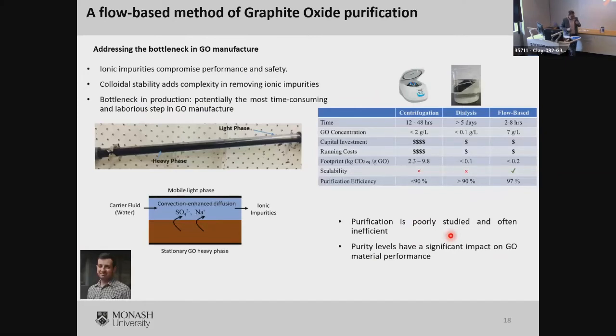I know that everybody uses graphene oxide in some form, but it turns out that the purification of graphite oxide is a pretty difficult thing to do. And I'm giving you some examples here. Centrifugation, if you do it in the lab, takes 12 to 48 hours, dialysis would take you 5 days. The flow-based method, which PETAR developed, took us 2 to 8 hours. Capital costs are minimal. The carbon footprint is minimal. Scalability is massive. So what he did was, again, this is not graphene oxide, but graphite oxide.